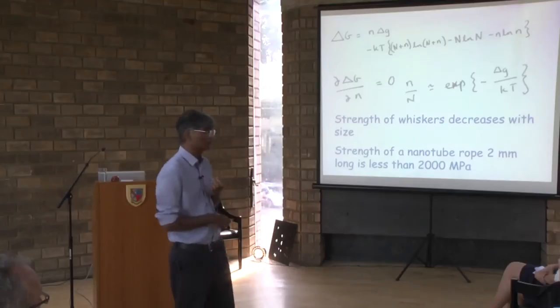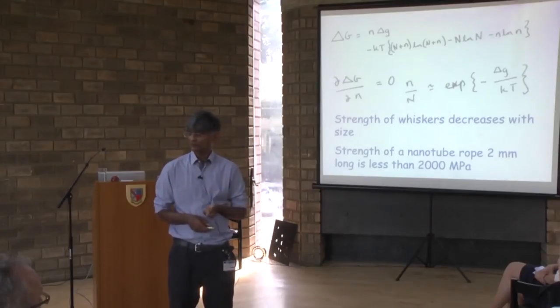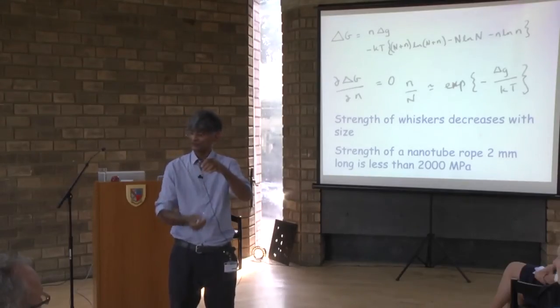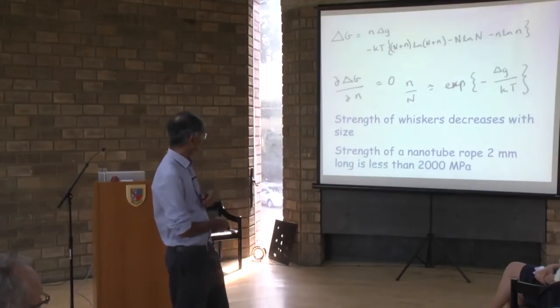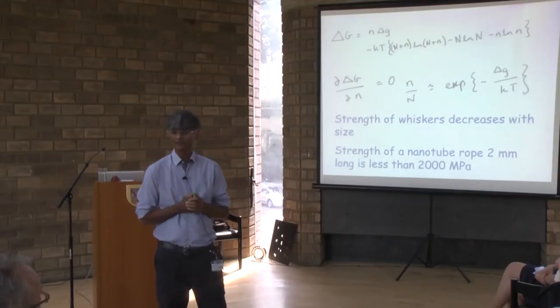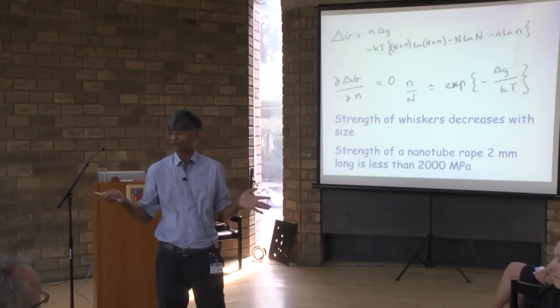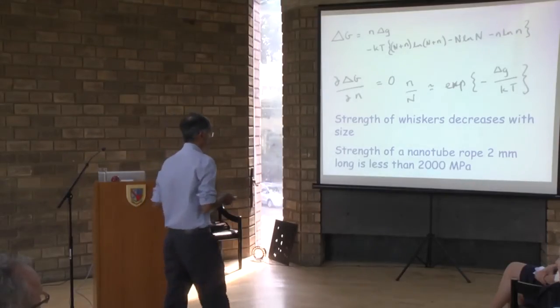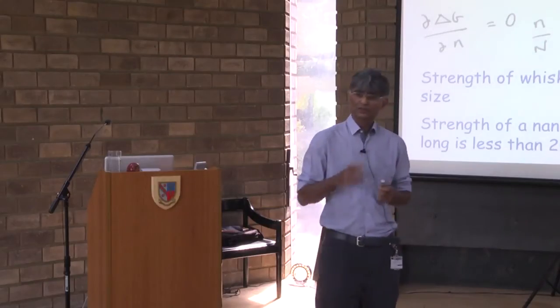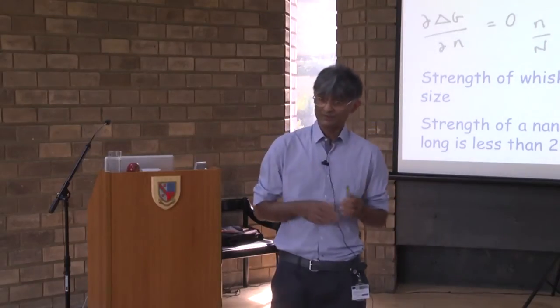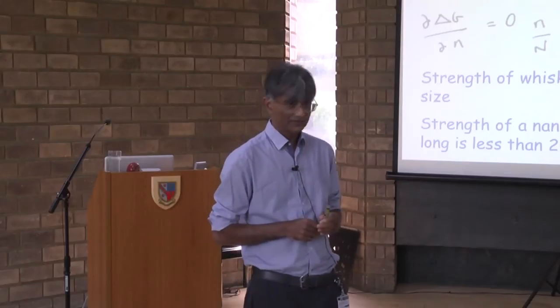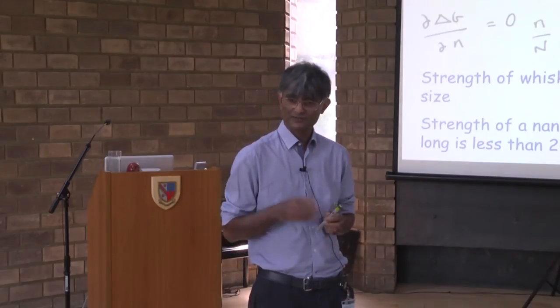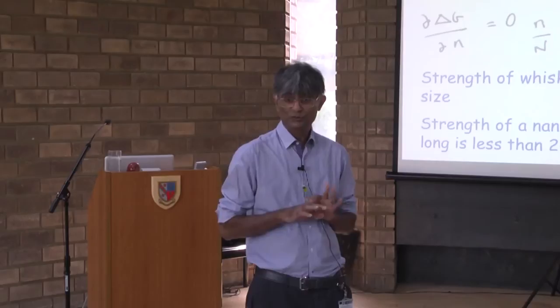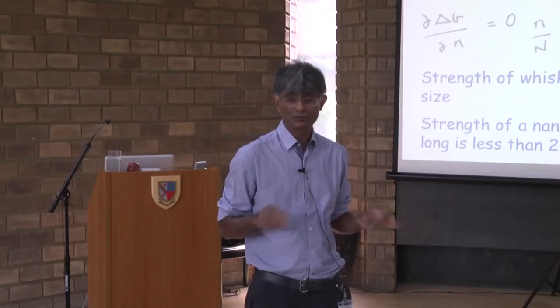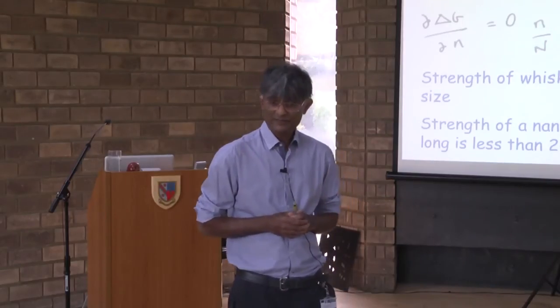If I increase the number of atoms in my sample, the number of defects will increase, and that is why the strength collapses. And there's no carbon nanotube rope greater than 2 millimeters, let alone 120,000 kilometers, which can beat steel. So I wrote a paper. This was inspired by this discussion in Darwin from one of the lunchtime talks, and I sent it to NASA. So no one any longer talks about space elevators.